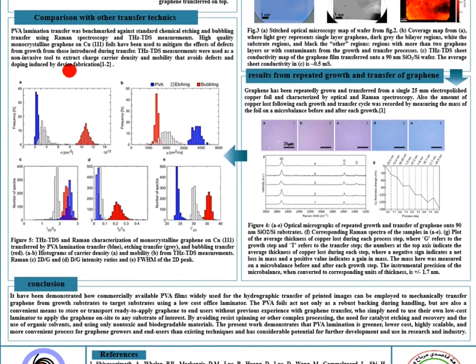The comparison of PVA lamination transfer with standard chemical etching and bubbling transfer, using Raman spectroscopy and terahertz TDS measurements, demonstrates that etching and bubbling transfer have a greater detrimental impact on graphene properties as compared to PVA lamination transfer.